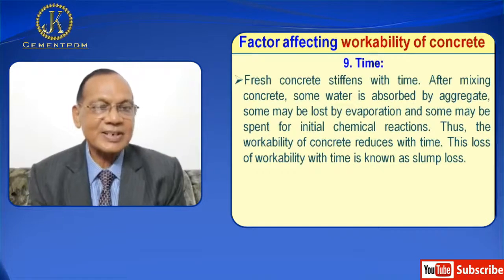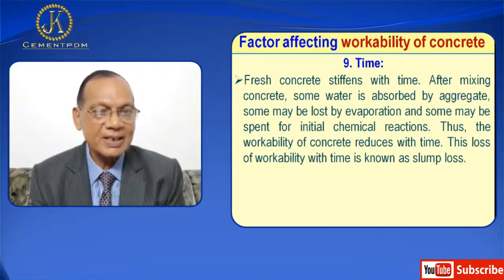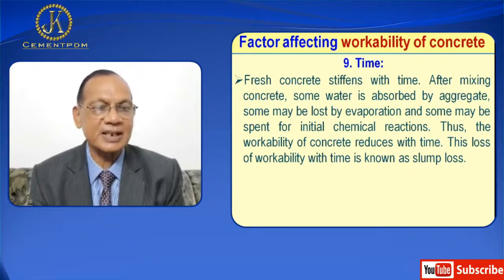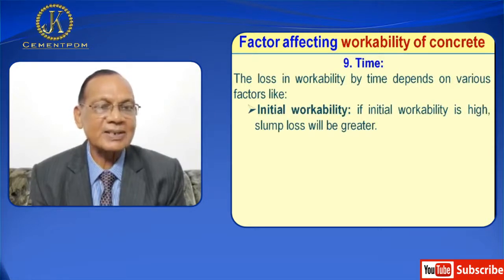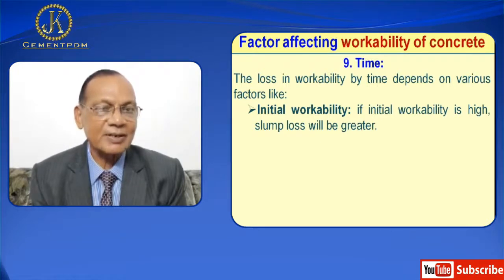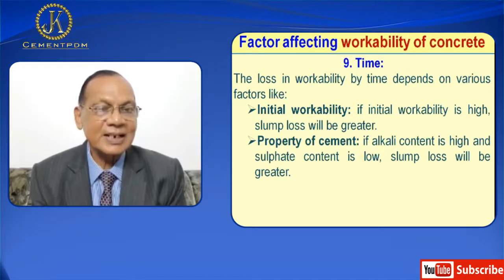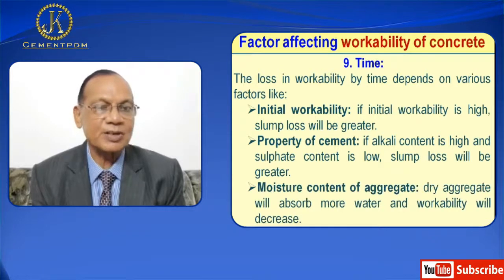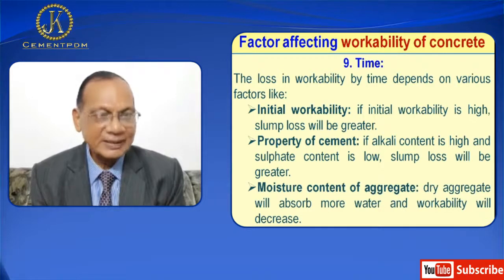Next is time. Fresh concrete loses workability with time. After mixing concrete, some water is absorbed by aggregates, some may be lost by evaporation, and some may be spent for initial chemical reactions. Thus the workability of concrete reduces with time. This loss of workability with time is known as slump loss. The loss in workability depends on various factors: initial workability — if initial workability is high, slump loss will be greater; property of cement — if alkali content is high and sulphate content is low, slump loss will be greater; and moisture content of aggregates — dry aggregates will absorb more water and reduce workability.